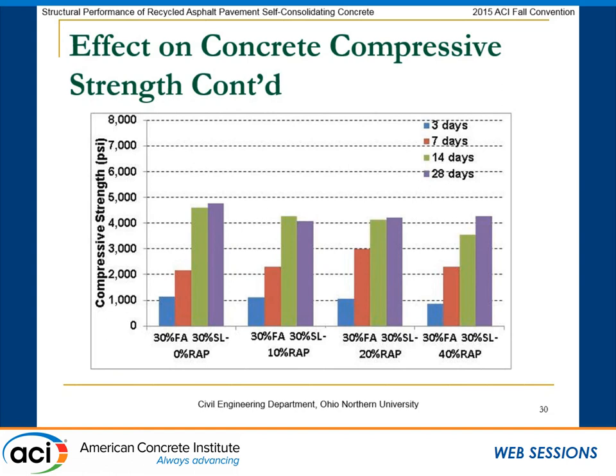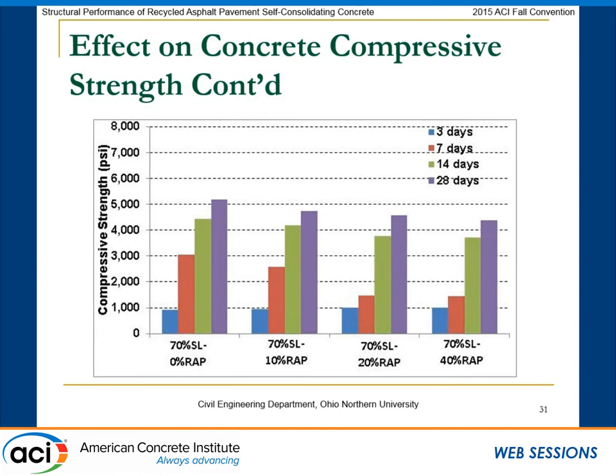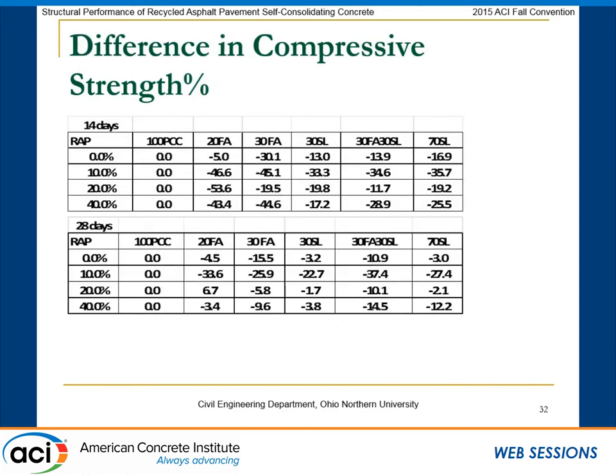So we have reduction here, and as the RAP content increases, your compressive strength decreases. Okay, and then for 70% slag, this is close to the 30% slag, and both of them are close to the 100% Portland cement, and as the RAP content increases, your compressive strength decreases. So here, this shows the percentage of difference between the different mixes and the 100% Portland cement mixes at 14 days and 28 days. As you can see, all of the mixes show smaller strength than the 100% Portland cement mixes, either in 14-day